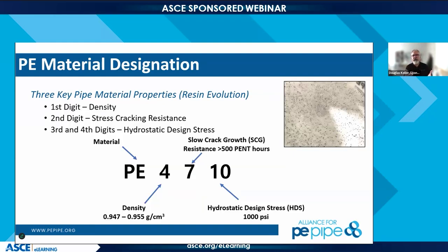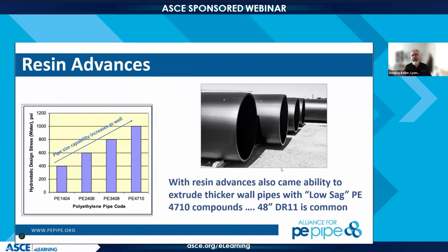So what does PE 4710 mean? Well, PE is polyethylene. The first digit refers to the density. As we talked about, density controls our tensile strength and our stiffness. It also is a controlling factor for our pressure class and pressure rating of the material. The second number is the slow crack growth resistance. This is a test that we perform in the laboratory at elevated temperatures. The minimum value for a class 7 is greater than 500 hours. Now, most of the material, and we'll see on the next slide, is well above the 500 hours. And then the 10 refers to the hydrostatic design strength of the material.